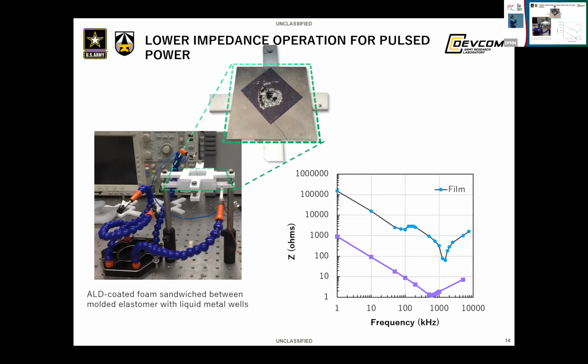So one of the arguments for this is that we have lower resistance. So it could actually be thought of as a pulse power substrate. And I don't know where my other legend piece went, but here's the foam impedance, and here is a film from that wafer of what you would get from a deep trench kind of pulse power configuration etched out of silicon. So that part works out pretty well.